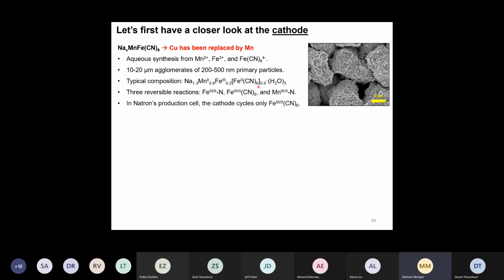And then we have the hexacyanoferrate group, which is iron in the 2+ state, and Fe(CN)6. And this material also contains some water in the interstitial sites. And now with this structure, we basically have a couple of reversible reactions that can happen. So you could imagine that this iron, which is coordinated to the nitrogen, can change its oxidation state between 3+ and 2+. You can also change the oxidation state of the iron that is coordinated with the carbon from its 2+ state to a 3+ state.